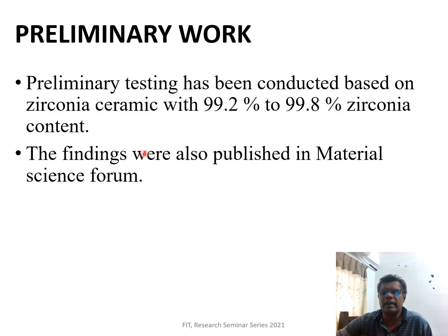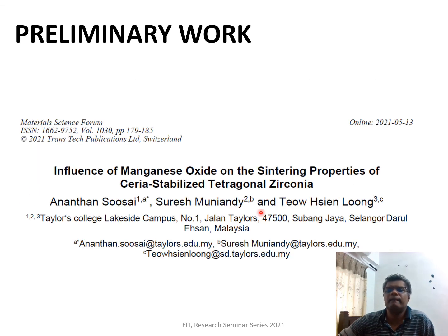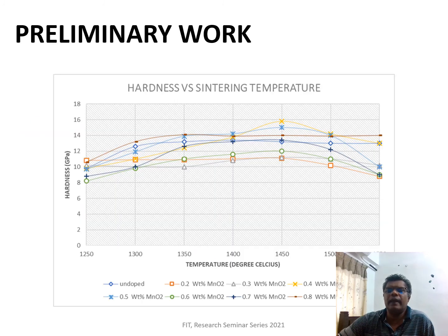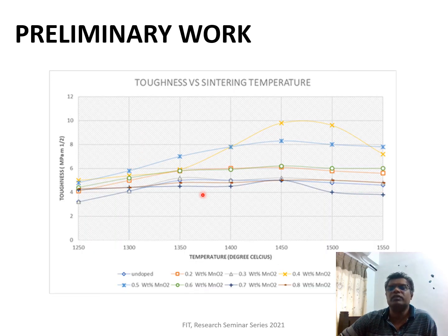So in the preliminary work, currently I've done preliminary testing by conducting a composite with 99.2% to 99.8% zirconia content, and the findings were also published in Materials Science Forum. The paper has been published, and the hardness of the composite has been discovered for different amounts of zirconia, and the toughness also has been investigated and found that the toughness and hardness have been improved quite significantly compared to the normal powder preparation. And the grain size was found to be significantly reduced, to close to 500 nanometer.